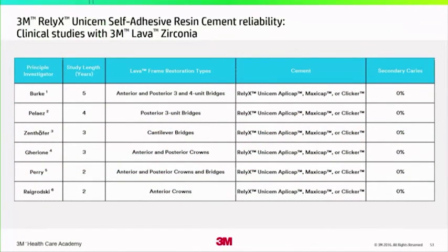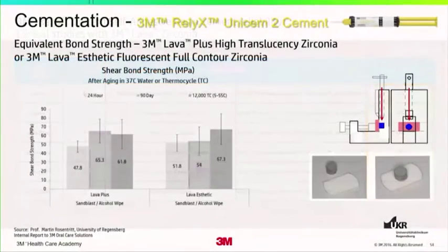There's a lot of evidence out there that tells us that self-adhesive resin cements are more likely than not to be the preferred way to adhesively cement zirconia restorations in place, because the incidence of failure with these is actually quite low. There's a number of other examples that have been done and shown to prove that the bond strength with Unicem 2 is actually quite good with the Lava Plus, and we have no expectation that this is going to change, as you can see here with the Lava Esthetic as well. Very high flexural strength and very high compressive loading.